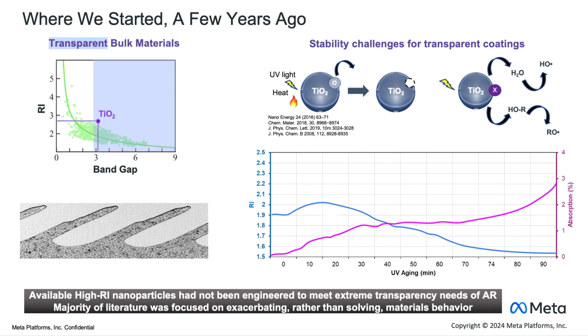We started really paying attention to this maybe 8 or 9 years ago, right, when the field of AR started growing a lot. And our approach or our strategy back then was to simply look at the dispersion of all available materials, comparing refractive index versus band gap, and try to find the highest refractive index material in the transparency window. So obviously that's titanium dioxide. There's a lot of commercial sources already, and so we started sourcing them, us and many others. And very quickly, we applied them to make very complex, high-quality nanostructures. In this case, what I'm showing here is nano-imprint lithography of some SRG gratings containing titanium nanoparticles.